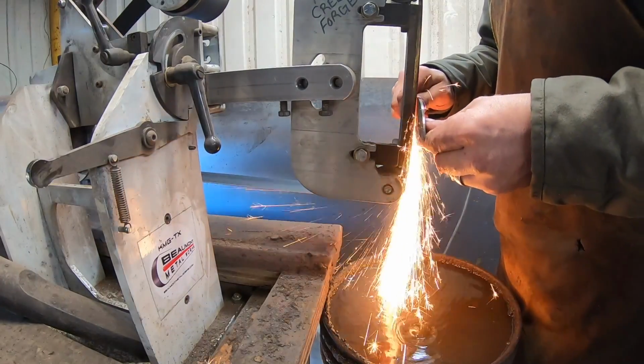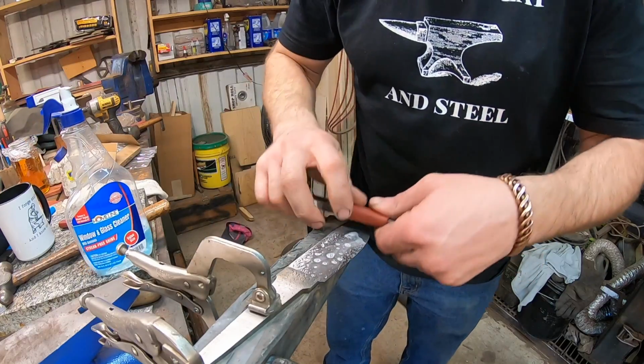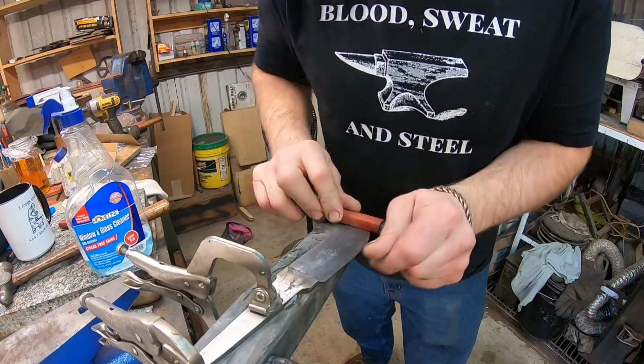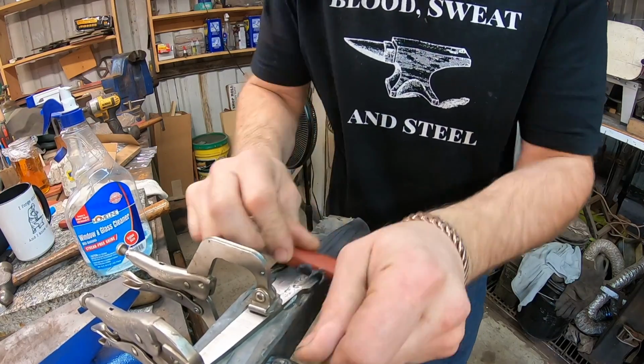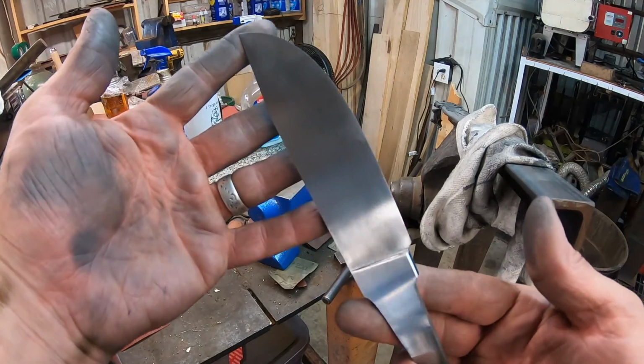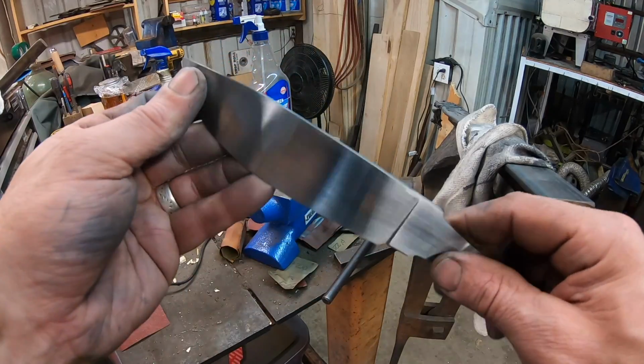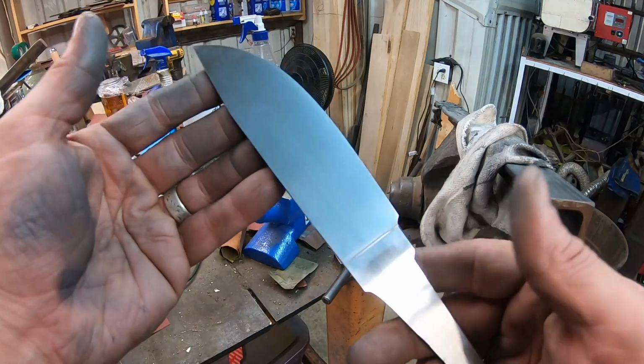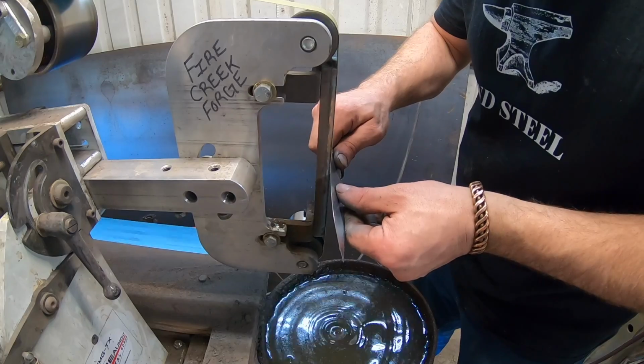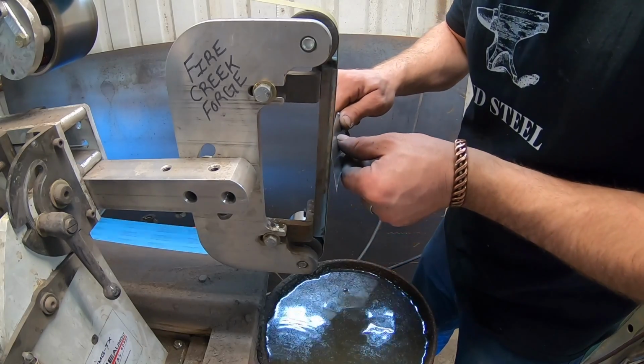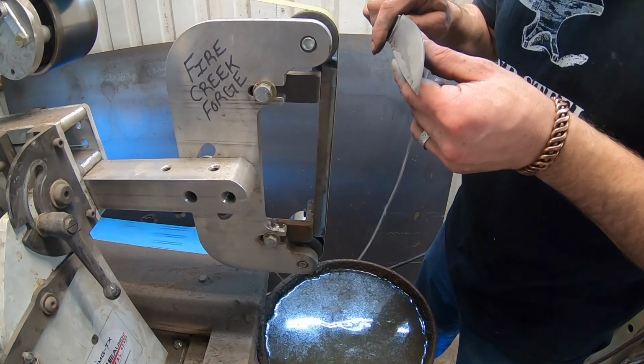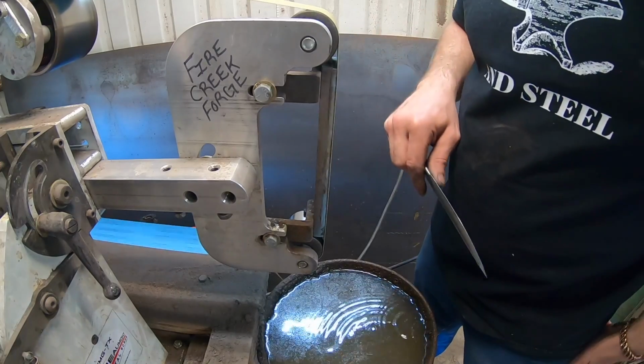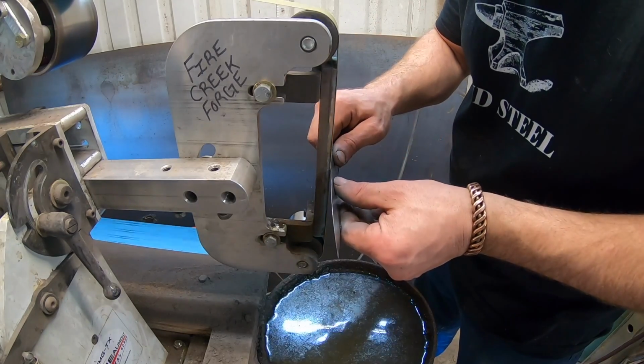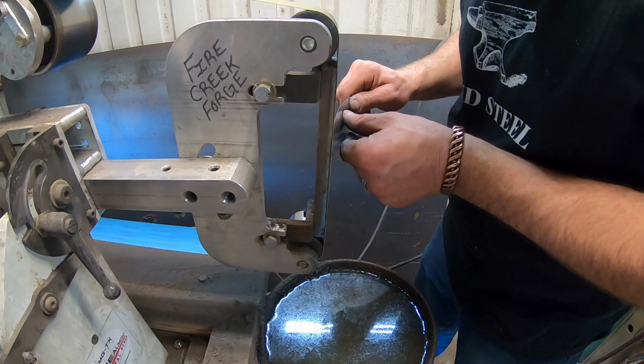I left the blade pretty thick actually, and that was helpful because this allows you to hone everything in and get the profile where you want it to. And I had to do some more grinding on one side than the other, but the profile turned out pretty nice. So we have a hand sanded blade here, and it's ready to go into the etch to reveal our pattern. But first I'm going to do an edge test.